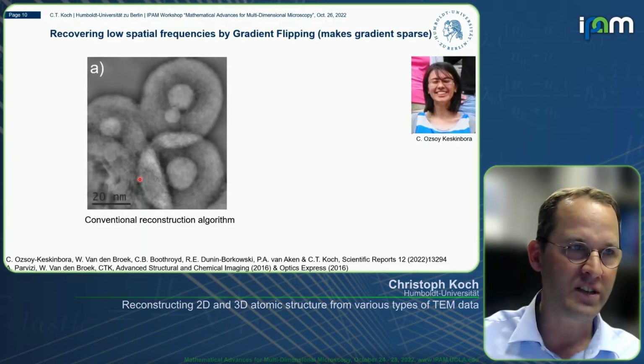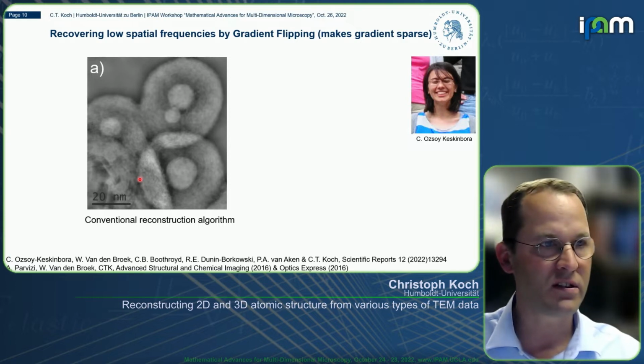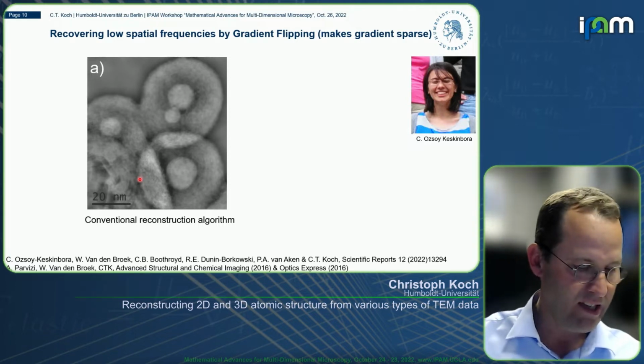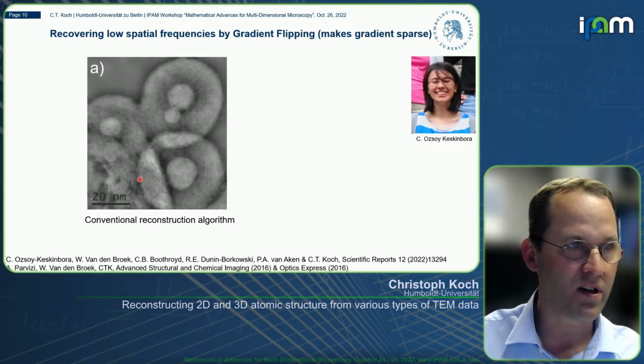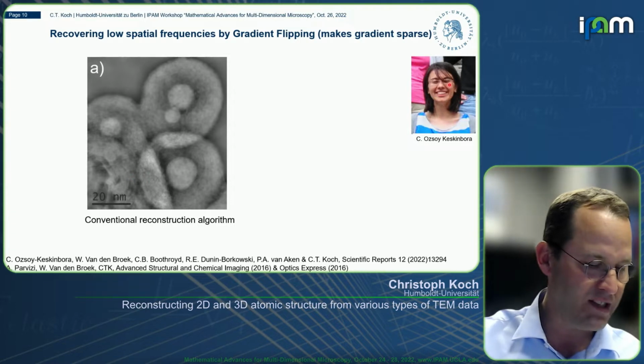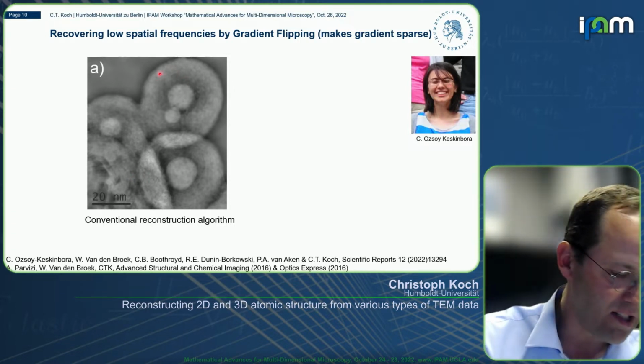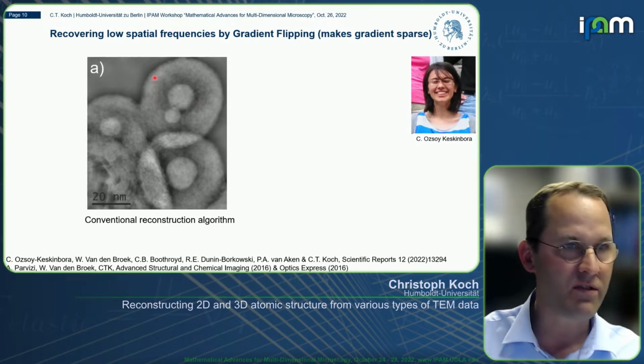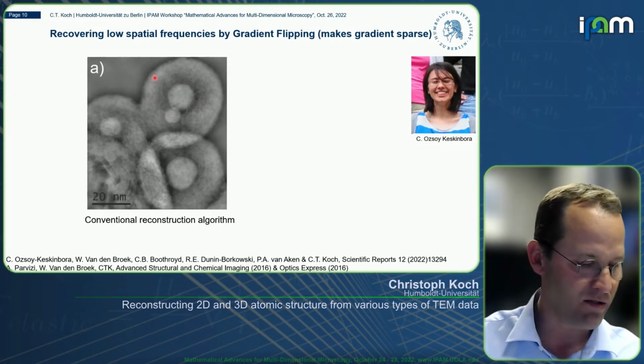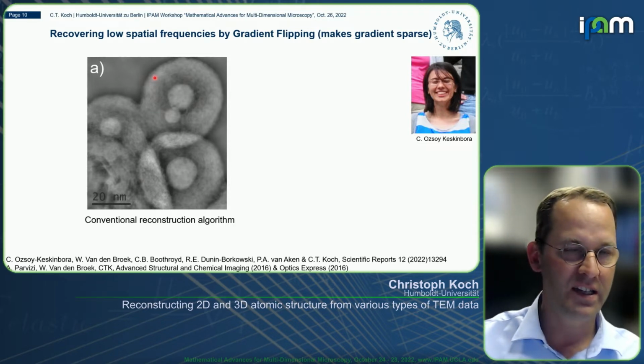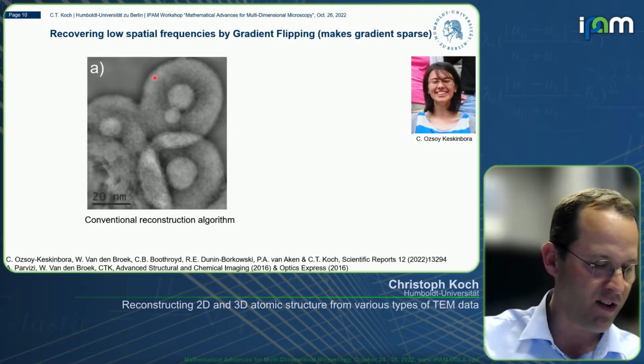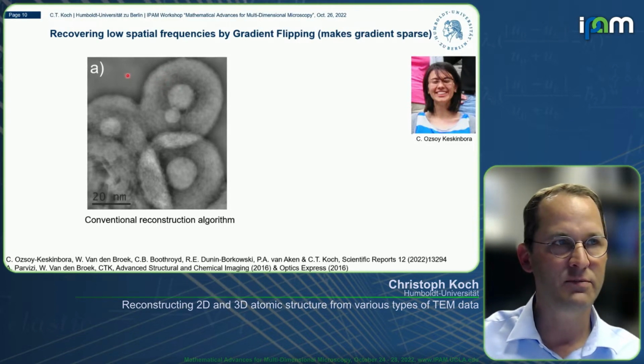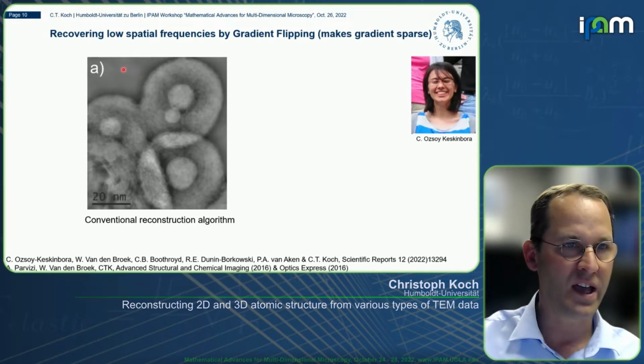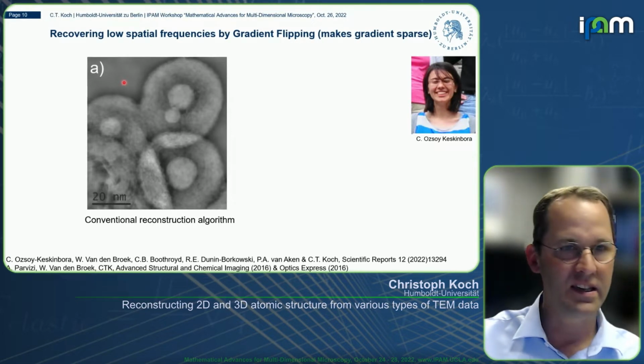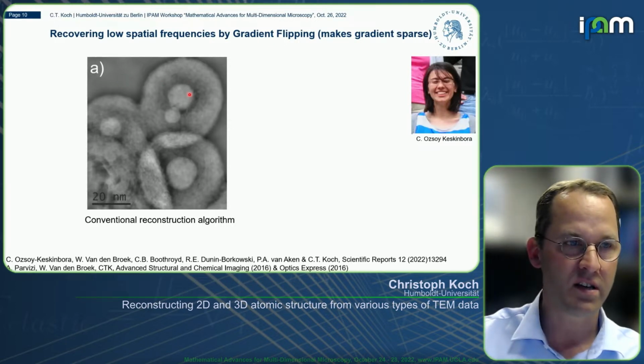And if you acquire a focal series, for example, these are now iron core filled carbon nanostructures that C. Ozsoy-Keskinbora has acquired some data of. And what you can see here, you can nicely see the atomic structure. Well, yeah, you can see maybe not atomic resolution, but somehow there are some layers of this carbon material. But there's something missing. And it is actually that the gray levels inside the material somehow vary, and they're roughly the same as outside. And you would expect outside to be vacuum, so there should actually be a phase shift relative to what's inside. And that is just missing in this picture because the low spatial frequencies are missing.